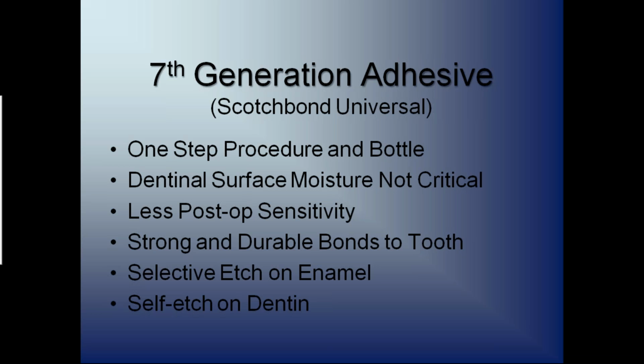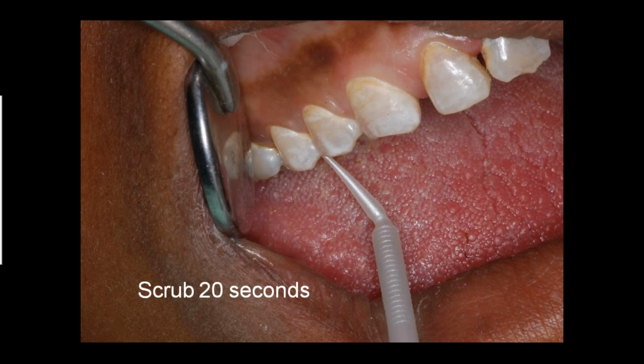We'll talk about selective etch and then the self-etch on dentin, and there's a lot of rationale for using it that way and still getting similar, if not better, bond to dentin by using the self-etch portion on the dentin. The pH of phosphoric acid is about 1. The self-etch Scotch Bond is about 2.7, so that's where we have to go ahead and consider the use of selective etch. So after we've done our preparation, we're going to go ahead and take our adhesive. As I mentioned, we're going to scrub it in there for 20 seconds, allow complete impregnation of that particular dentinal surface with our adhesive. Scrub it, make sure it infiltrates properly in there.